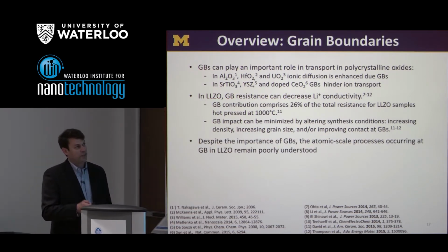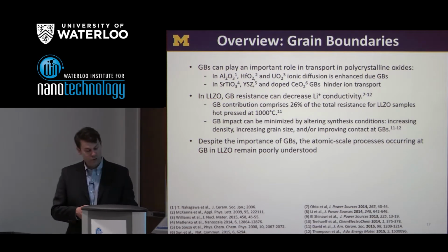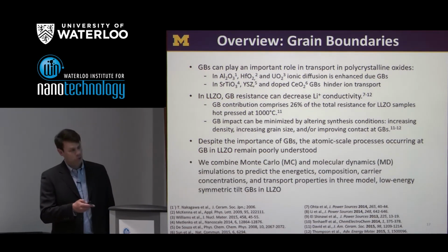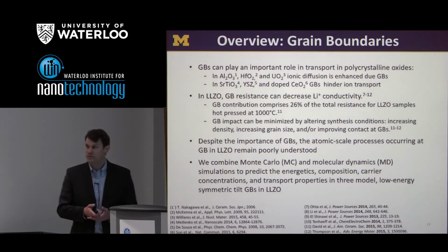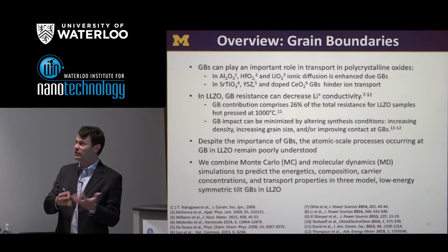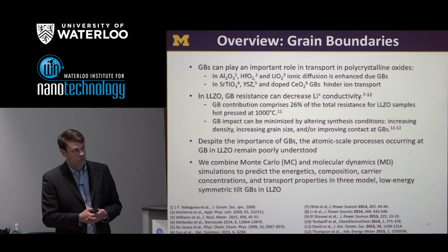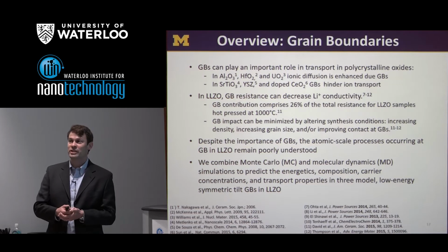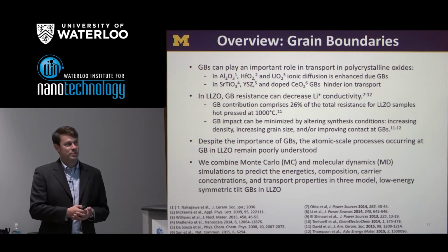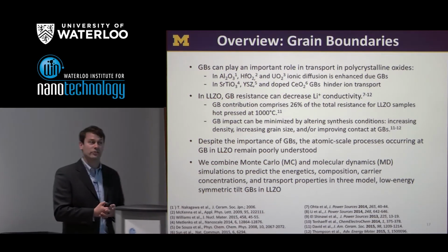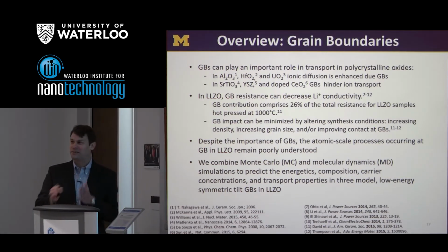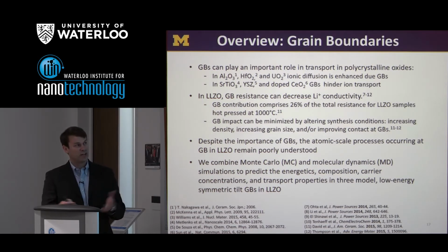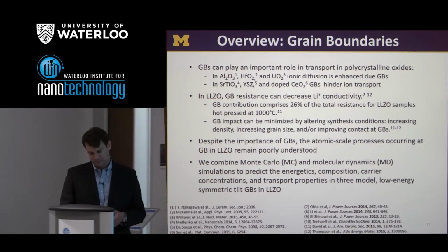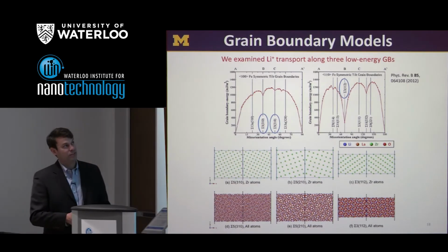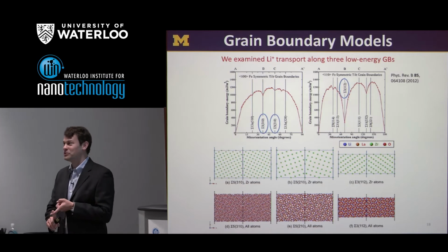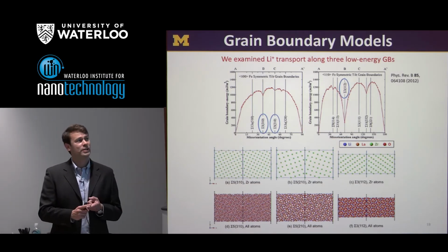So what we would like to do is look at what's happening at these grain boundaries and understand the transport there using Monte Carlo and molecular dynamics. This is different from the density functional theory calculations I mentioned earlier, which were a quantum mechanical technique. These are classical simulations. We have a prescribed interatomic potential. We go classical in this case because these are very large simulation cells, on the order of, say, 2,000 to 15,000 atoms, necessary to get a grain boundary-like region and a bulk-like region in the same simulation cell. So one problem is that even though bulk transport in LLZO has been widely studied, as I mentioned, not much has been done for grain boundaries.